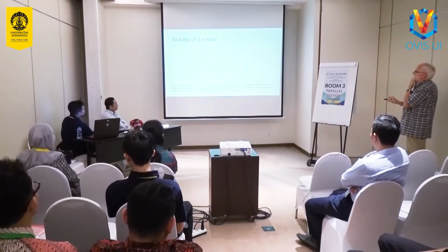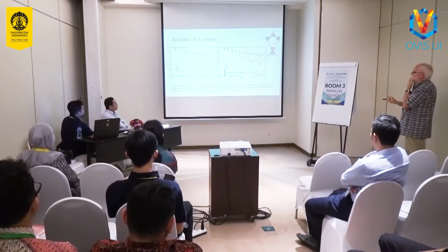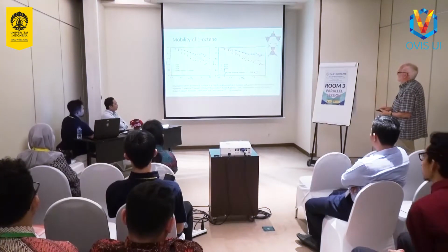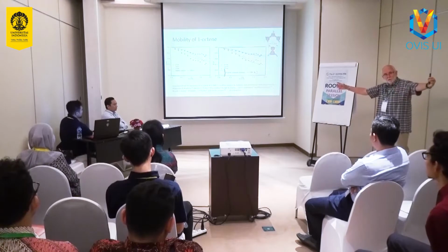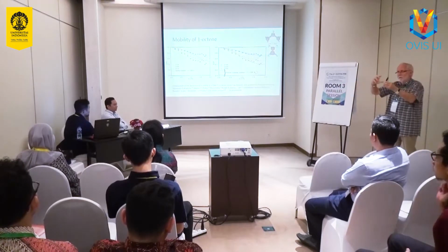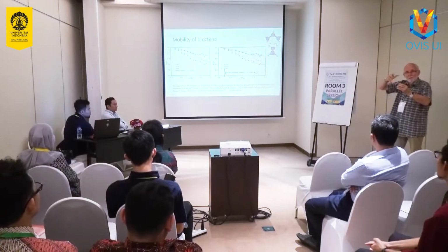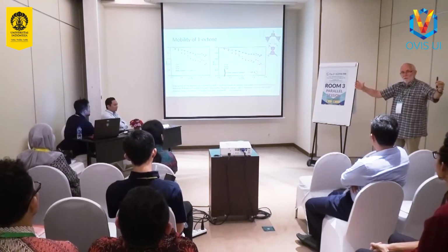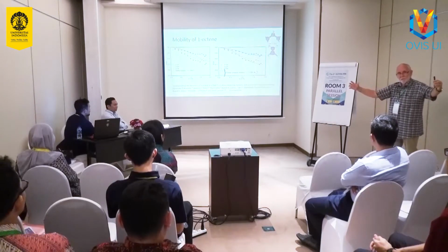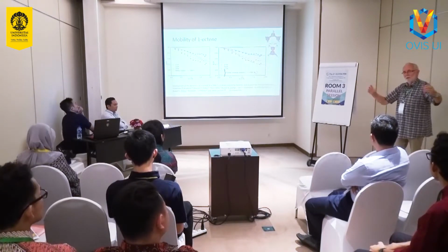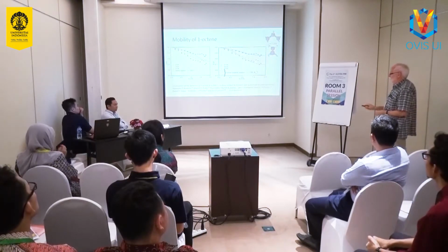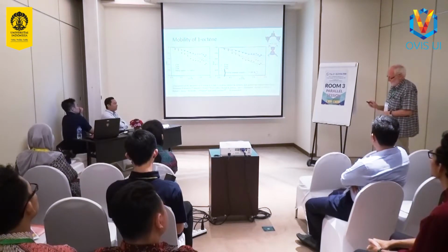And we could also, by fitting the curves to a model, conclude that the nature of the mobility was actually the methylene groups in this long chain hydrocarbon oligomer wiggling. We fit the data to that particular kind of motion. So the molecule itself is a long chain oligomer which is stuck in the zeolite pores, but it's wiggling. And that wiggle is responsible for what we see in quench.